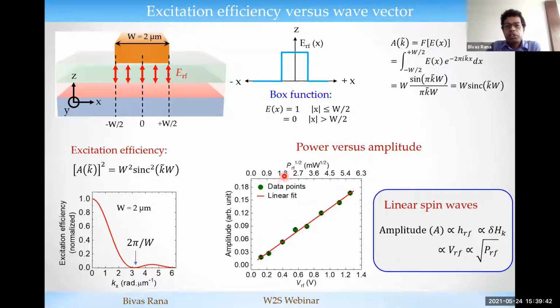One of the important features of this VCMA-induced spin wave is that the amplitude of the spin wave is linearly proportional to the gate voltage. It's quite natural because the amplitude of the spin wave, in the linear approximation, should be linearly proportional to the magnetic field you are applying to excite it. Here we are not directly applying a magnetic field, but modulating the perpendicular anisotropy. That means it should be proportional to the change of the anisotropy of the system, and that is essentially proportional to the gate voltage we are applying. That is the reason we get this kind of linear variation of the amplitude as a function of the gate voltage.